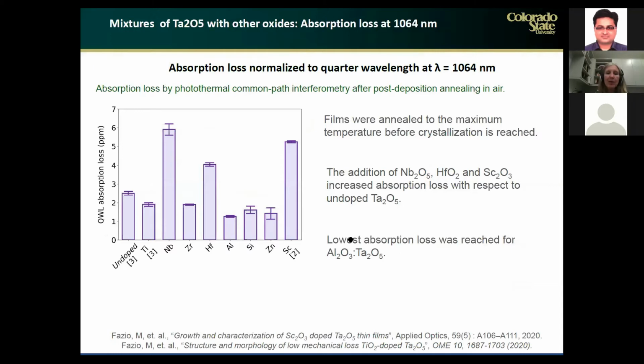So what about the absorption loss on these mixtures? I tabulate here the absorption loss at 1064 nanometers, and these are on the annealed samples, annealed at a temperature just below the crystallization temperature, so the sample is not crystallized. The values of the absorption loss have been normalized to quarter wave thickness for comparison. This is undoped, or just plain tantala. This is the absorption loss of tantala when it's mixed with titania. Again, this is our model material. And so adding titania also reduces the absorption loss. But when we add niobia, the absorption loss increases by about a factor of 2.